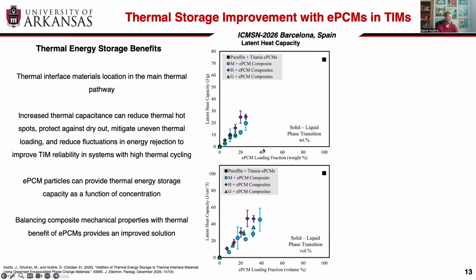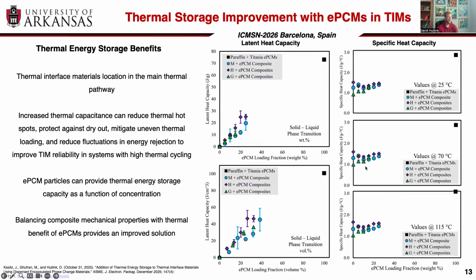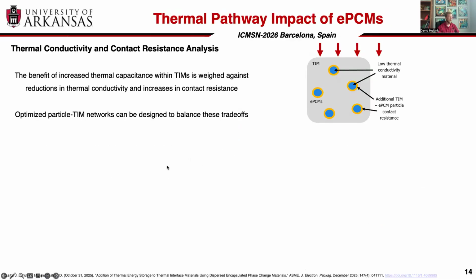And of course, like we saw in the silicone gel, the increase of particles proportionally affects the latent heat capacity of the materials. And we also see impacts in terms of the specific heat capacity, so we can see the overall thermal capacitance of the system increase through adding ePCMs into the composite mixture. But again, this can't be viewed in isolation because there are other effects in terms of thermal conductivity of the material and its contact resistance.